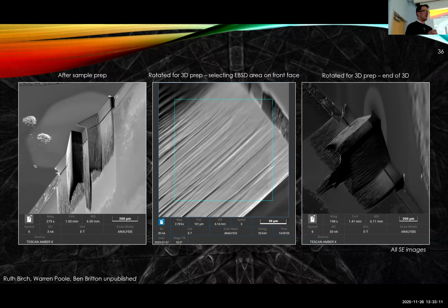In a 3D EBSD experiment, what we do is page by page, we remove the surface of this material. So we use the focused ion beam, a xenon probe, to remove the surface layer, typically between 2 and 200 nanometers for each slice. And then we EBSD the clean surface, and we repeat this experiment many, many times. This is a very early experiment, so it does look way better in the newer stuff, and Ruth has some super exciting, very large data sets, but this is one that we're very happy just to show as a taster for you folks of what you can do.